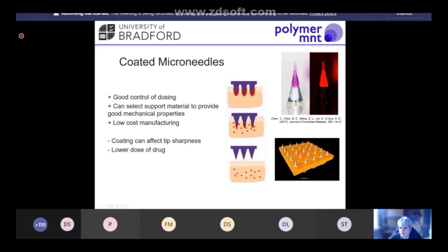So we've got some examples here of where this is a polymer-based microneedle again that's been dip coated to give this coating on the tip of the needle. Once again, as long as our coating process is robust and repeatable, then we can get good control of the dosing into the skin. We can get high quality delivery of the active ingredient in these layers into the skin. As I said before, we can select a support material, so the mechanical properties can be chosen to provide good mechanical behavior and good penetration behavior into the skin.